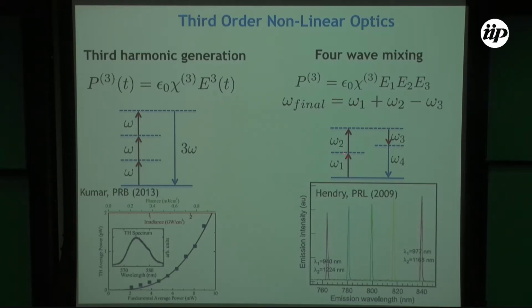So we have absorption of omega 1, omega 2, omega 3, and then your material is going to emit omega 4 energy. This has also been done in graphene back in 2009. People have observed the 4-wave mixing signal from graphene. It's also a very strong signal. They change the wavelength and the intensity doesn't change so much. That's because the graphene absorption is almost flat in this energy range.